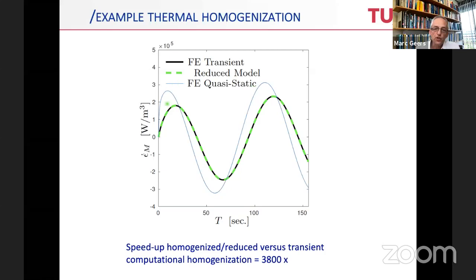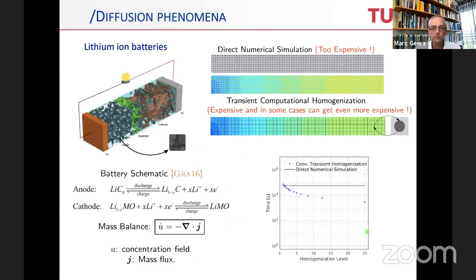The quasi-static one, in which you would ignore the extra contribution of the emergent continuum, is the blue line. And then the reduced model, which is the emergent continuum, is the green dashed line that basically falls on top of the finite element transient problem. So what we can see is that this reduced continuum, which has these emergent properties, performs equally well as the transient problem, but it's about 3,800 times faster. So we're really at a point where model reduction and emergent continua become alike. It's a kind of applying a model reduction, but if you look at it clearly, it actually leads to an emergent continuum.